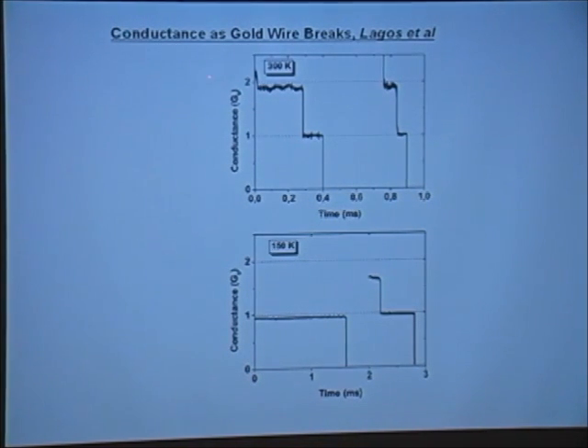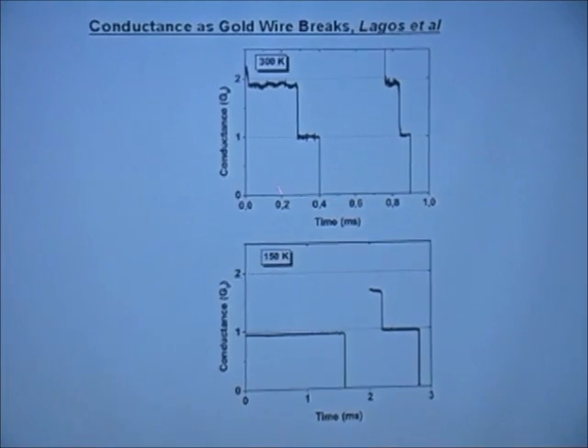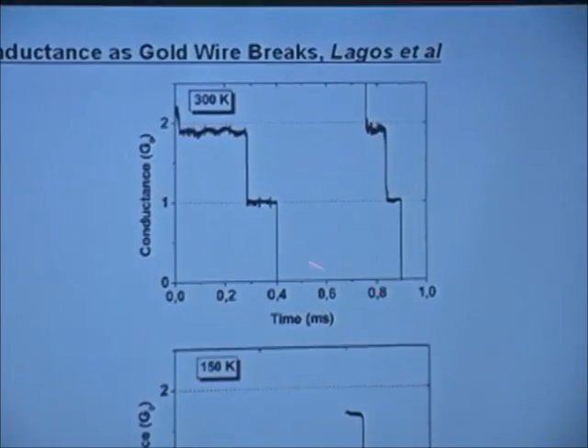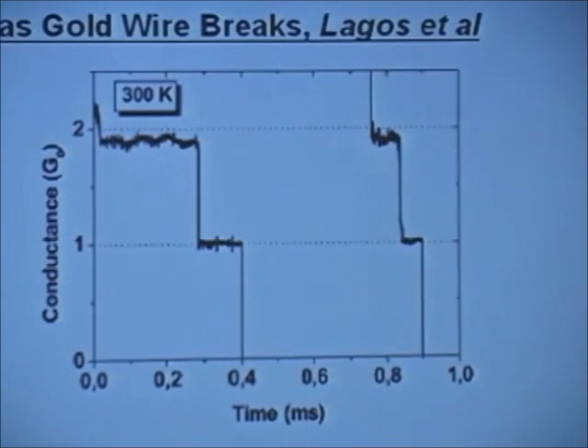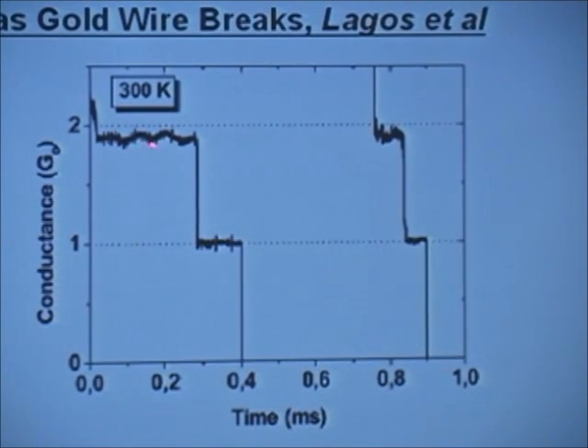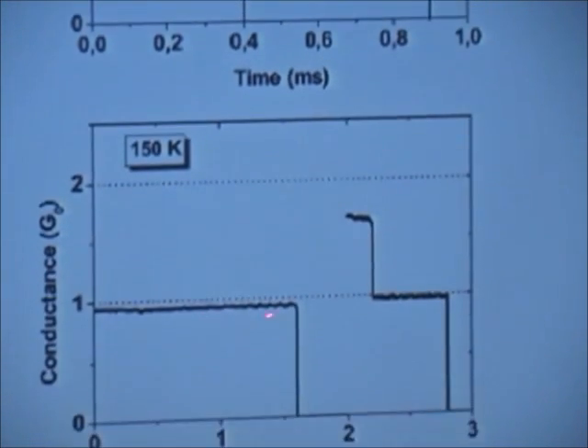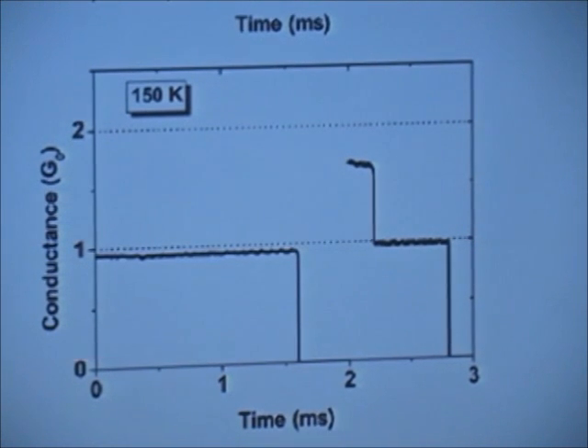This is an example of a gold wire from these authors here. This is room temperature. We're stretching the wire at a constant rate with time, so we plot the conductance as a function of time, in milliseconds. And you can see what happens. It sticks at this value. That means essentially the contact is 2 atoms wide, then we break to one atom wide, and it snaps. That's another sample. At lowish temperatures, it's more stable. We can go on like that. See? Very flat, very flat. An example of a macroscopic quantum effect from a very simple system.